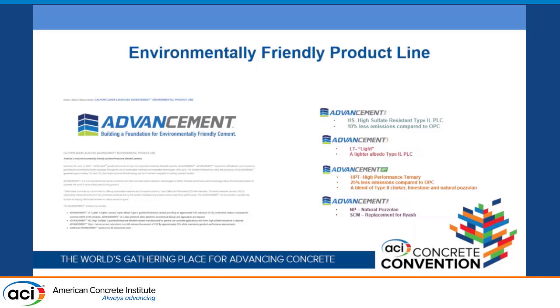We have our Advancement LT, which is made with Type 3 clinker, but with interground limestone. It's very light colored, really low iron, high alumina, and very well received in architectural work. And then we're working on Advancement HPT. This is a C595 Type IT cement, which will be ternary. We're going to blend our clinker with limestone and natural pozzolan to reduce that clinker factor even further to get a lower GWP. Then we also have the natural pozzolan as a standalone, which is a replacement for fly ash.